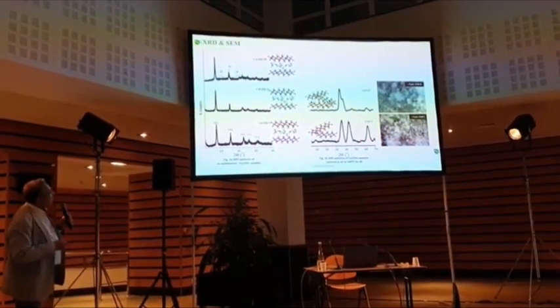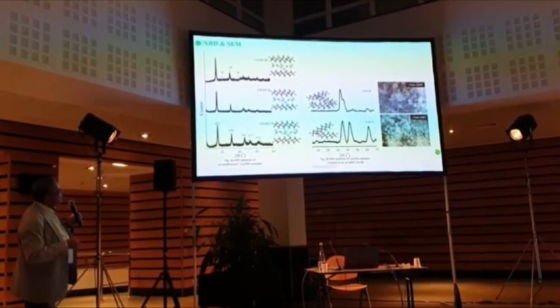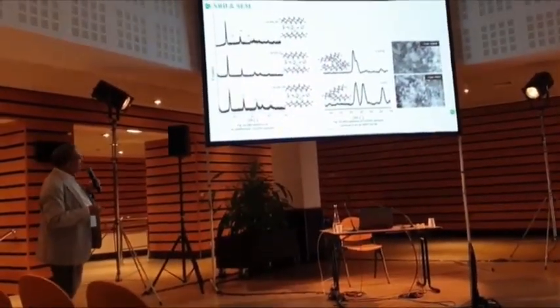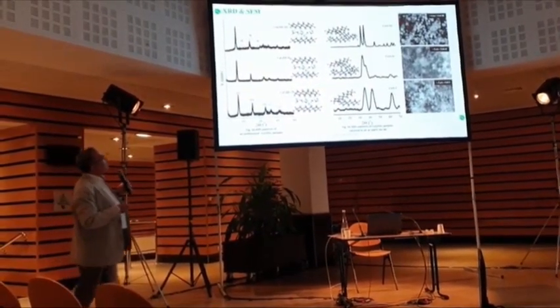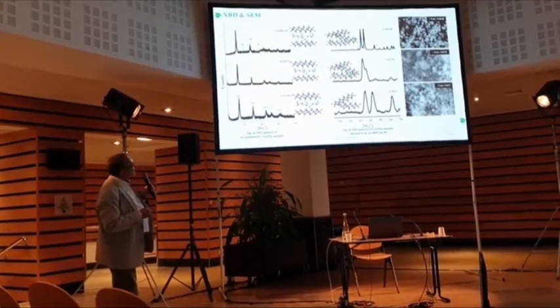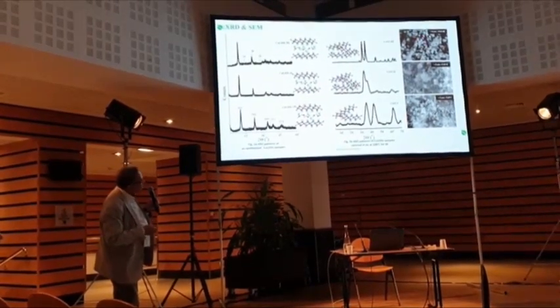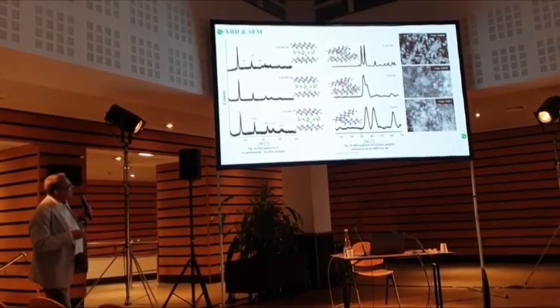And for catalyst 2, where there is more copper and less magnesium, we also have copper oxide material, just the crystal size increases a little bit for the copper oxide. And then for the last material, where there is no magnesium and only copper aluminum, we also succeeded in having the copper oxide supported, but now on gamma alumina. The particle size starts to become a little agglomerated and to increase. Here it's a more cloudy shape.